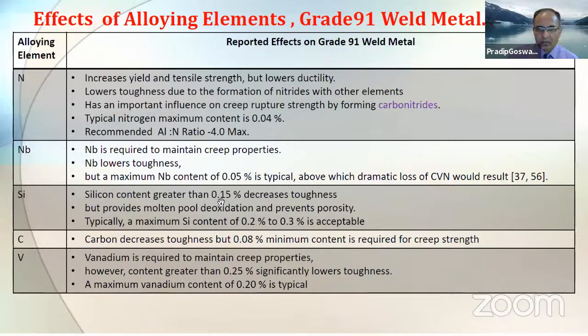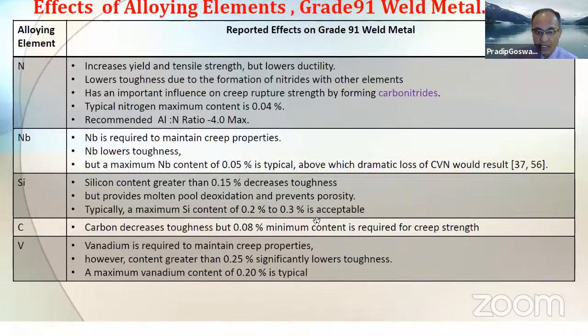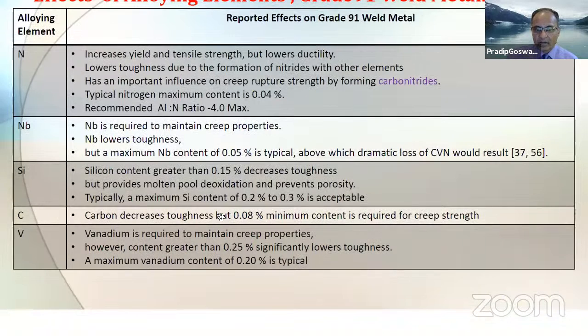Silicon greater than 0.15% reduces the toughness. But silicon is a good deoxidizer, and definitely it is needed for deoxidation and for prevention of porosity. Typically, a maximum silicon content of 0.2 to 0.3% is acceptable and allowed for this alloy. Carbon decreases toughness, but 0.08 is the minimum content required for the creep strength.